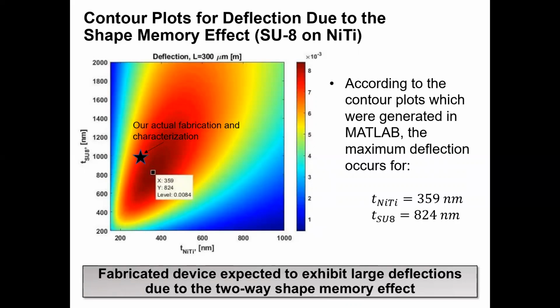In this case, the cantilever length is 300 microns as a function of the two design variables, the thickness of the SU8 on the left axis and the thickness of the NiTi on the bottom axis. The darkest red region corresponds to the maximum deflections expected, and the blue region represents the lowest deflections. The lower right region corresponds to a condition where the metallic SMA beam is thicker and thus more rigid, and imposes greater resistance to deflections induced by the shape memory effect.